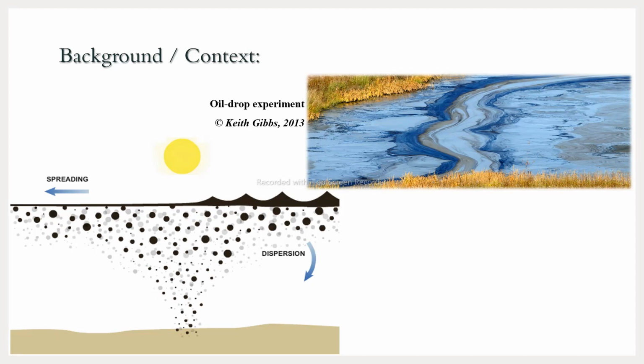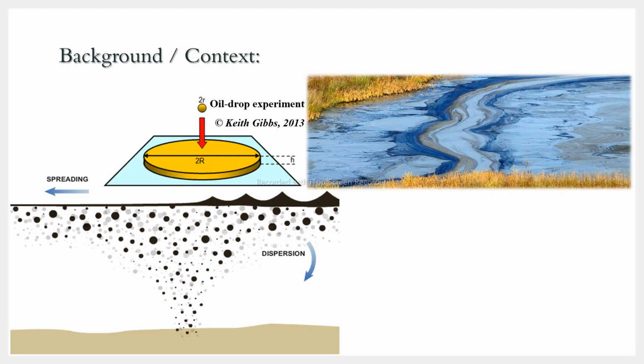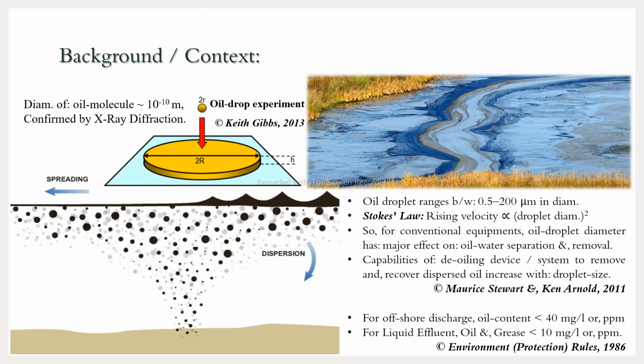There is one experiment called the oil drop experiment. Based on this experiment, the diameter of an oil molecule is found to be in the angstrom range, which was also confirmed by XRD studies for different oils. But the oil droplets are much bigger than that, at 0.5 to 200 micrometers in diameter.